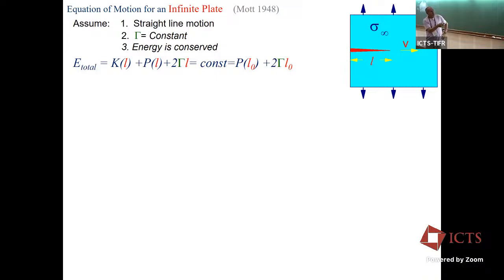Now we're saying since energy is conserved, once the crack starts to move, that's going to be a constant, and it's going to be equal to the potential energy when the crack just started to move, when the kinetic energy is 0, and that started at some scale L0. So at some scale L0, the crack started to move. Its potential energy was just this, and the dissipated energy was just 2 gamma times the same length L naught. And this is now going to be conserved.